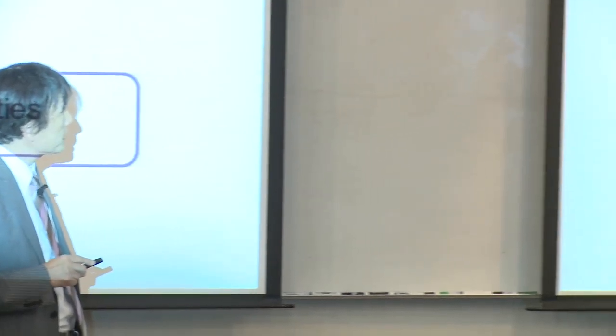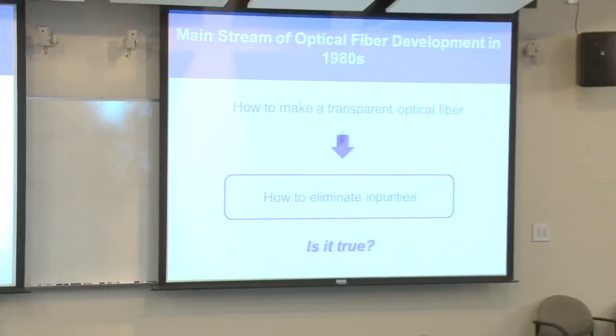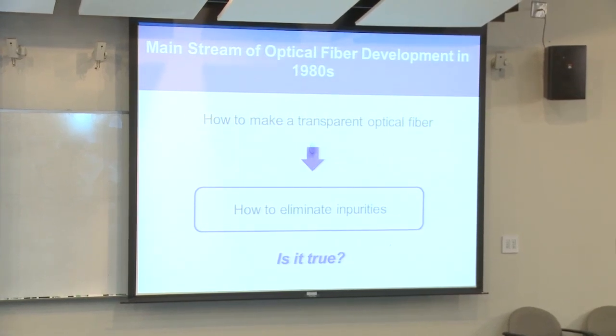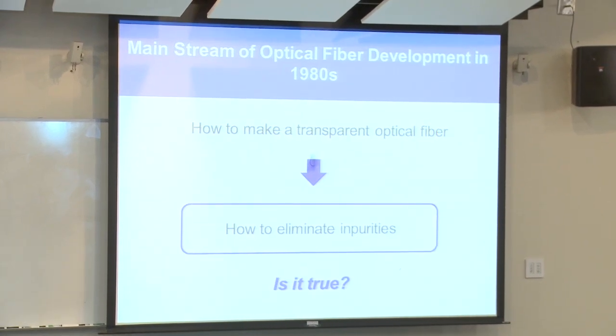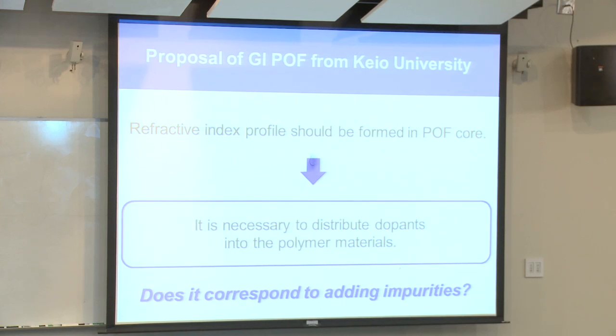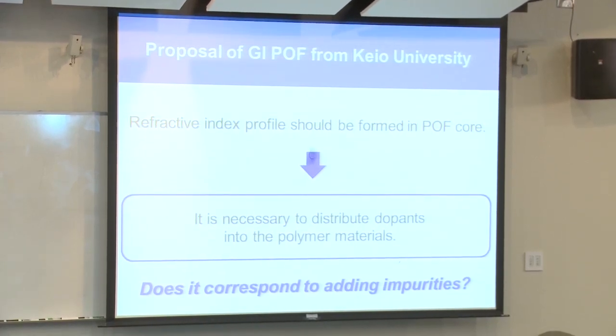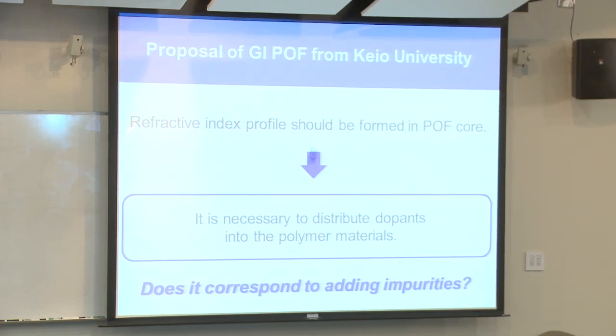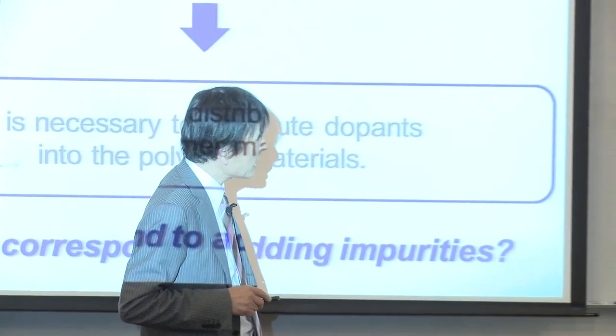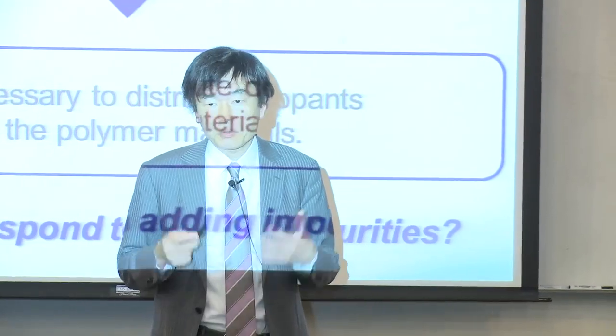At that time, the mainstream of optical fiber development in the 1980s was how to make a transparent optical fiber. In order to do that, the effort was how to eliminate impurities. But our proposal of grading the plastic optical fiber is a refractive index profile formed in the POF core region. That means it is necessary to distribute dopants into the polymer materials. Dopants should have a higher refractive index than the refractive index of the polymer matrix. And we have the concentration distribution in the radial direction. So we obtain a graded index profile.